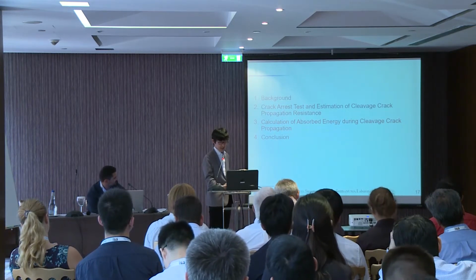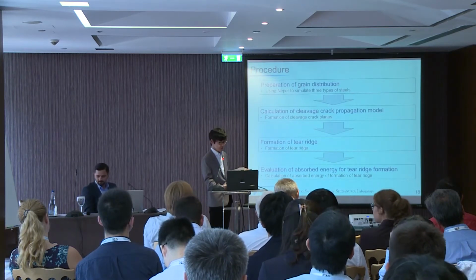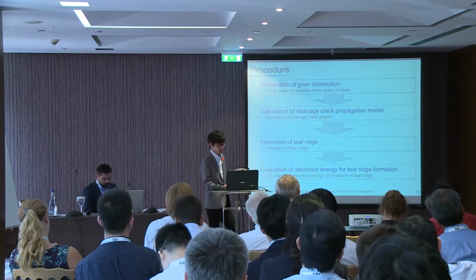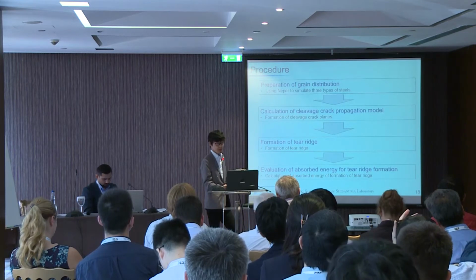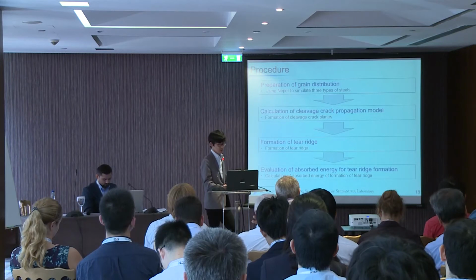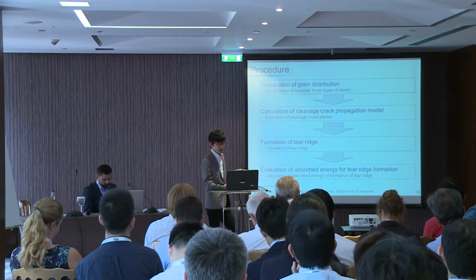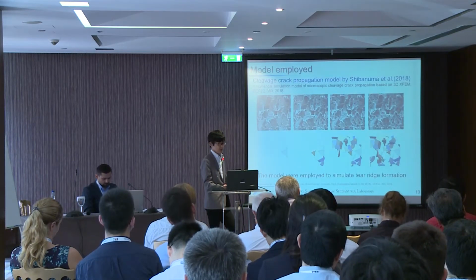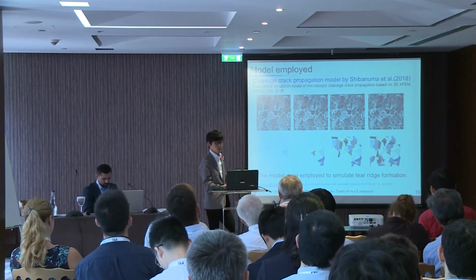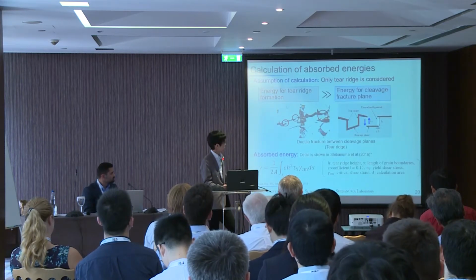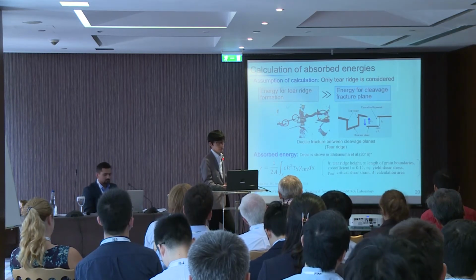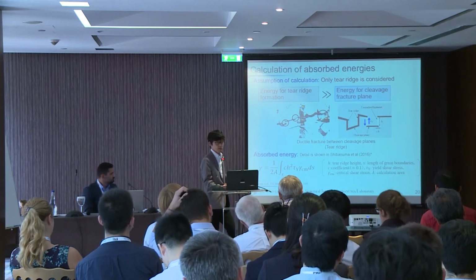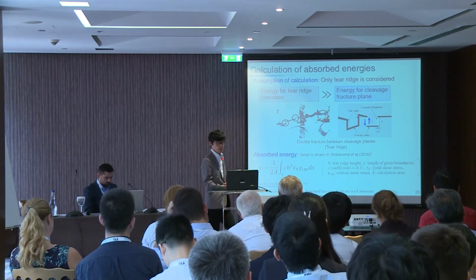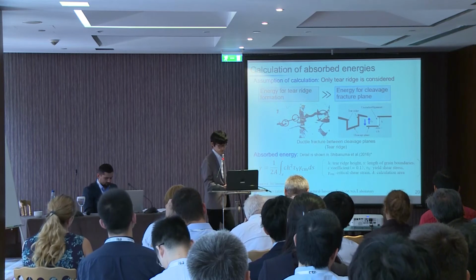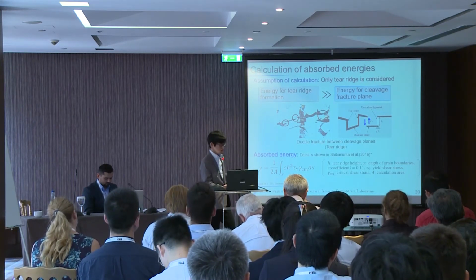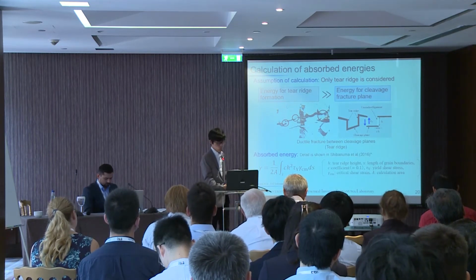We calculated absorbed energy during cleavage crack propagation. Procedure is this. First, we prepared grain distribution and calculated cleavage crack propagation presented by Shibanuma et al. in the previous session. And we simulated to form cleavage and evaluated absorbed energy. We used this model presented by Shibanuma. And energy for tear ridge formation is much bigger than energy for cleavage fracture plane, so we had better consider only tear ridge. And absorbed energy is this expression derived by Shibanuma et al. We used this expression.